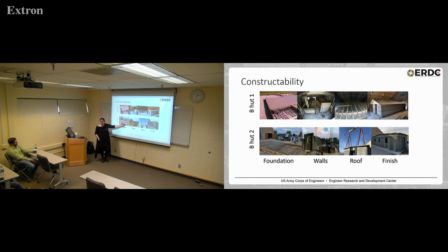Our second building, we still had a slab, but we put in anchor points while making the slab so that once we were done printing, we could easily tie the whole structure together. This building, which I'll talk about a little bit later, has a complicated geometry, but at the top it just goes straight. And so we could tie in a concrete poured roof, essentially, that we used formwork with, and just tie those in that way. And so when you talk about construction, you really can mix and match all the different kinds of construction you typically do for construction. And this applies across the gamut from everything from buildings to bridges to other infrastructure.